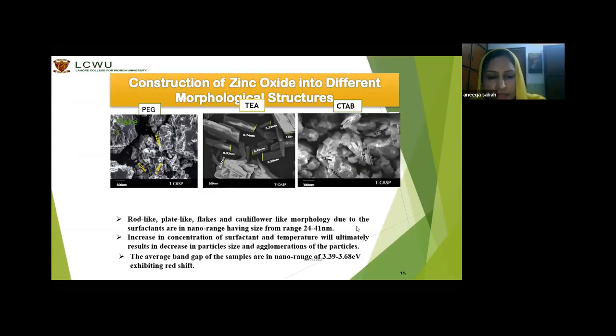Increase in concentration of surfactant and temperature will ultimately result in decrease in particle size and agglomeration of particles. The average band gap measured was within the nano range of 3.39 to 3.68 electron volt, exhibiting a redshift.